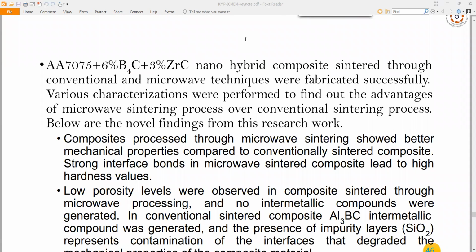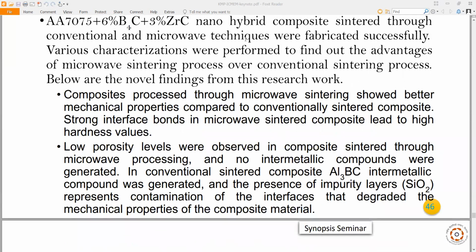And AA7075 6% B4C and 3% ZrC nano hybrid composites sintered through conventional and microwave techniques were fabricated successfully. Various characterizations were performed to find out the advantage of microwave sintering process over conventional sintering process, and below are the novel findings from the research work. That is, composites processed through microwave sintering showed better mechanical properties compared to conventionally sintered composite.